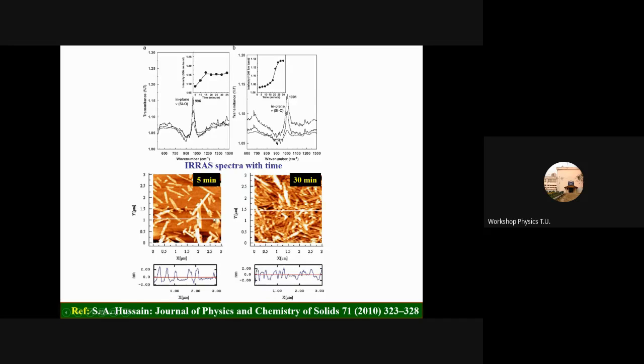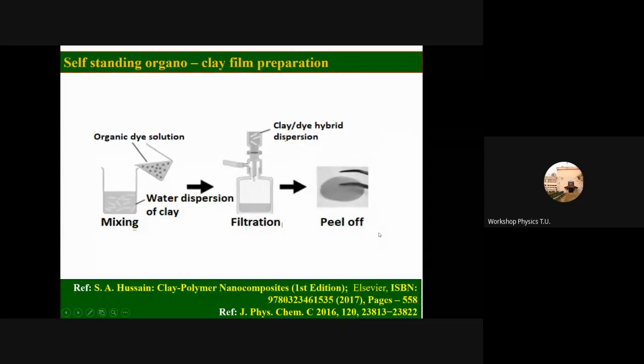Similarly, here I am showing two images. One film was deposited just after 5 minutes of spreading the dye molecule on the clay surface, and this one after 30 minutes, and you can see more clay in this image. That means it's a time dependent process, and you can get an idea using this kind of experiment.